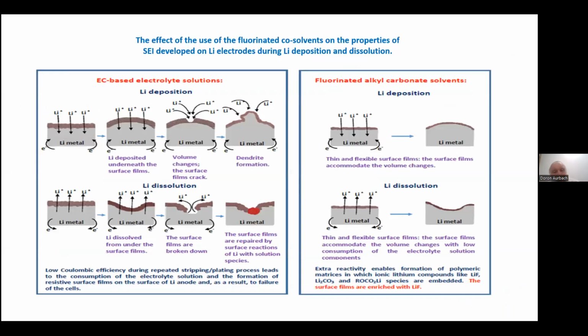So what happens with lithium? Lithium is always covered by a surface film. When we dissolve lithium, there's no way that the surface films will be flexible and uniform. So we always have places where we have cracks, and there's breakdown of the surface films, which means that we expose lithium to electrolyte solution, and then we have side reactions. So we have breakdown and repair, and this means that we lose more and more of the electrolyte solution. When we deposit lithium, we never have a uniform situation, so we form dendrites. And dendrites are very problematic. Again, we expose fresh lithium and a lot of side reactions.